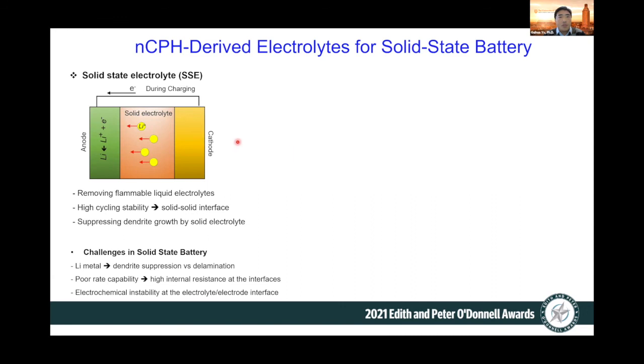So this is a very actively researched area. And the solid state battery has the potential for better safety and stability. So they can remove the flammable liquid electrolyte, and the solid-solid interface can potentially enable higher cycling stability and better suppression of dendrites. But still, many challenges remain in solid state batteries, including how to effectively suppress and avoid delamination of lithium metal. And also this solid-solid interface leads to higher internal resistance, which makes high rate, high power very difficult.